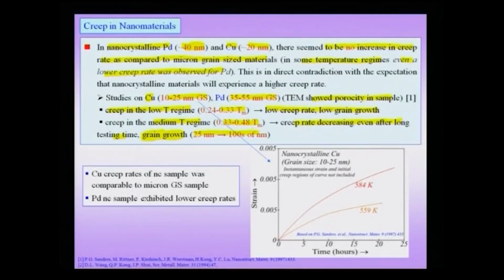And therefore, these are very serious issues associated with creep testing in materials, that often we do see porosity, often we see a lot of grain growth, and therefore, it is difficult to separate out the effect which is coming purely from the nano size grains vis-a-vis the changing structural parameters as the test is being conducted.